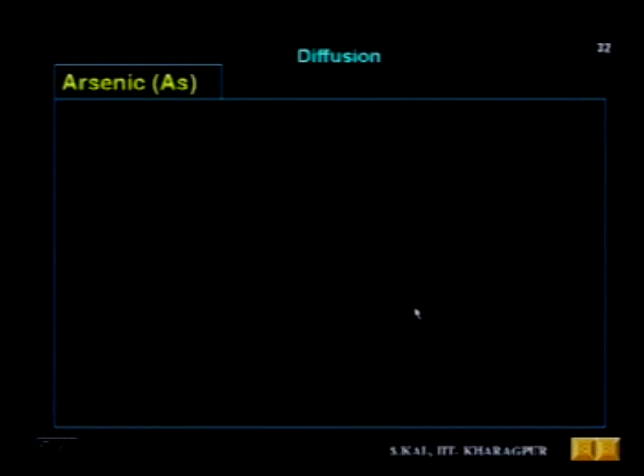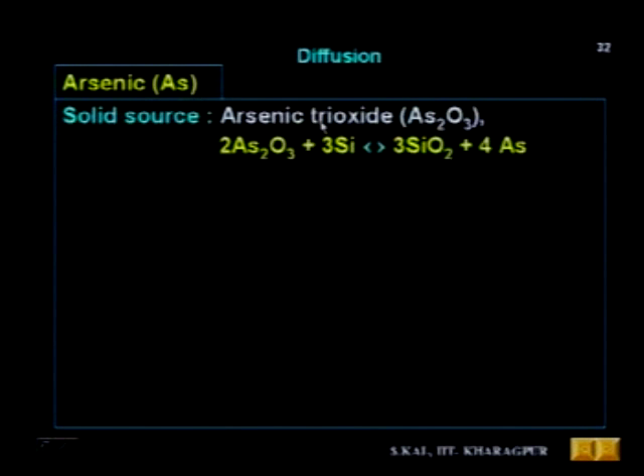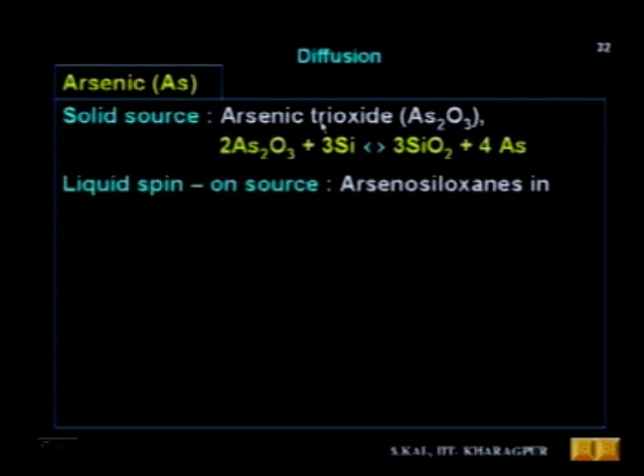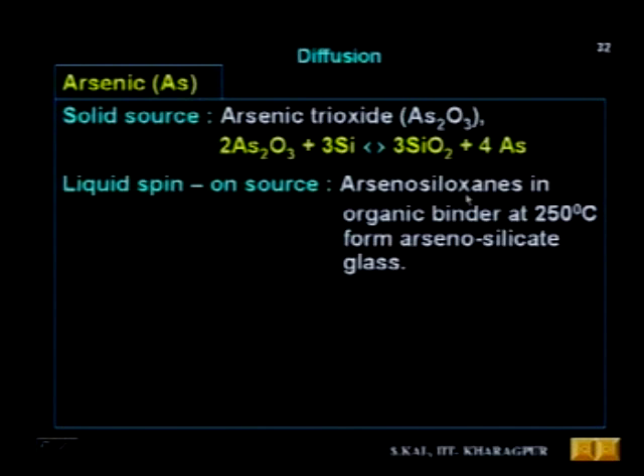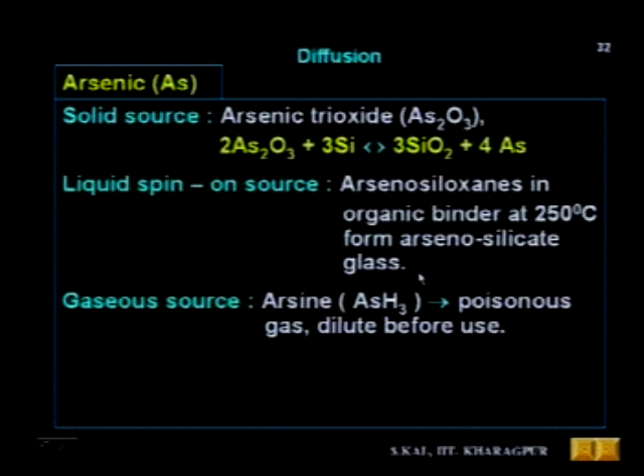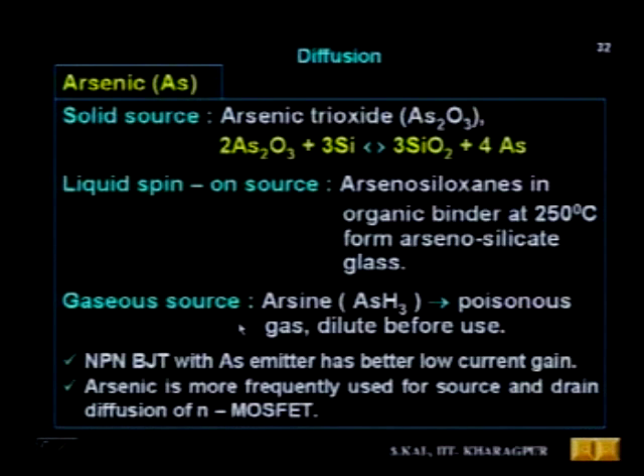Now we discussed about arsenic. And arsenic solid source is arsenic trioxide, As2O3. It has got also liquid spin-on source, which is arseno-siloxane in organic binder at 250 degrees centigrade. It forms arseno-silicate glass. That's why it is known as liquid spin-on source. Gaseous source of arsenic is arsine, which is AsH3, and the reaction is just like earlier cases.